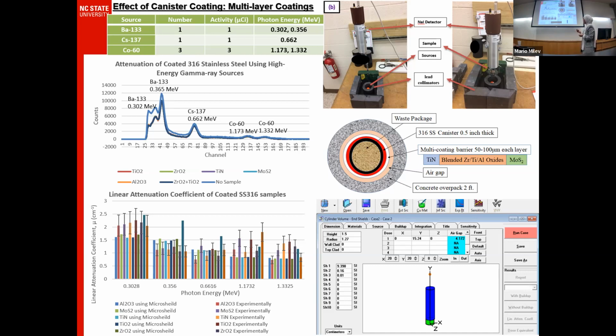The schematic shows the benefits of using multi-layer coatings on stainless steel. Titanium nitride can be used as a diffusion barrier coating. We can have blended zirconium, titanium, aluminum for corrosion resistance, and then a third layer of molybdenum sulfide as anti-crack. We also performed this study computationally using Microshield.